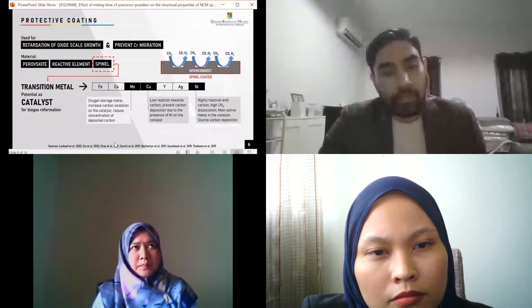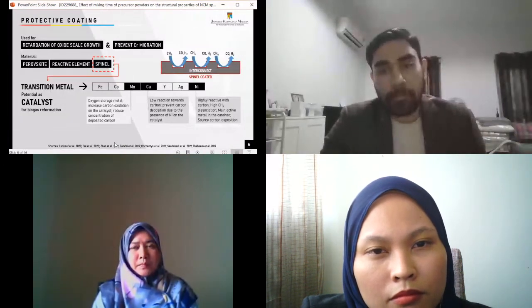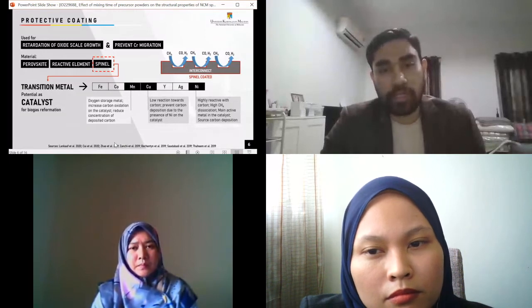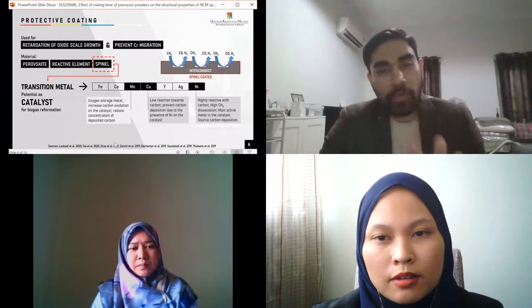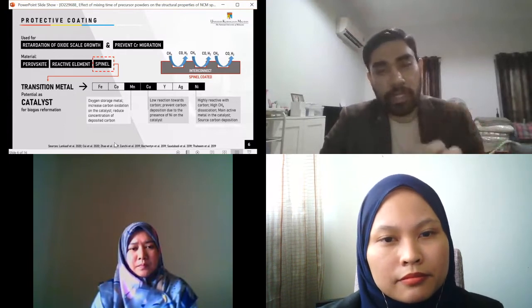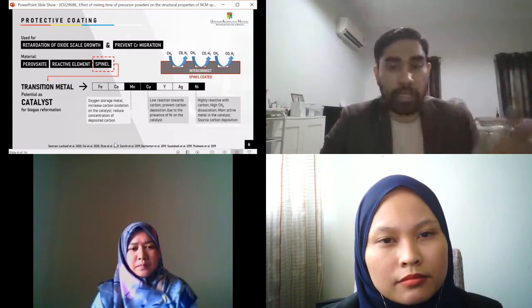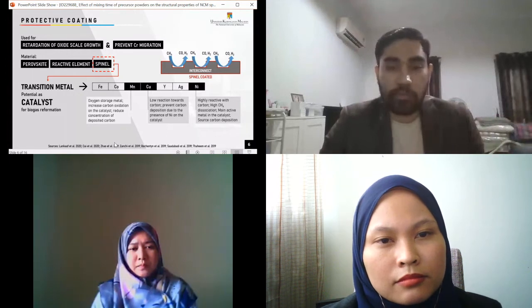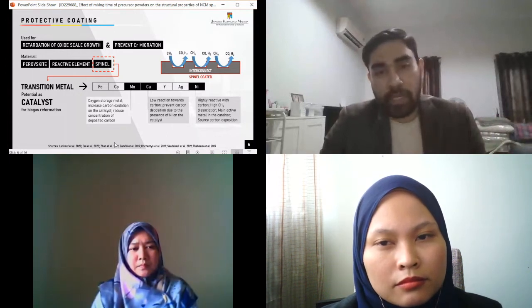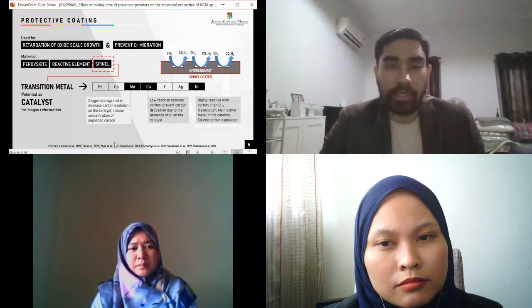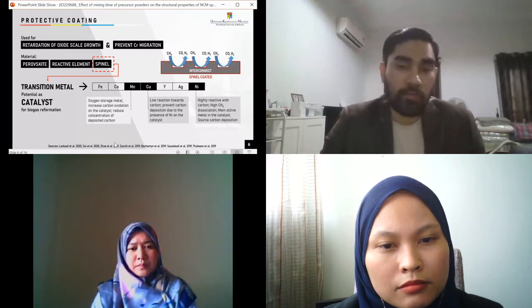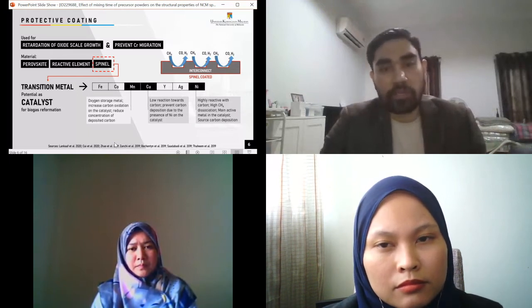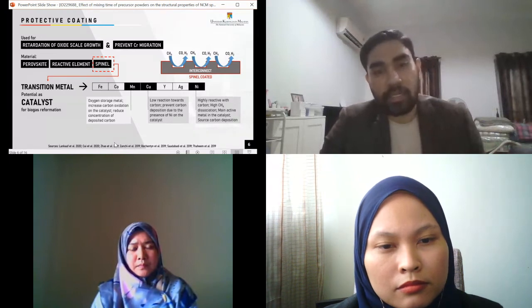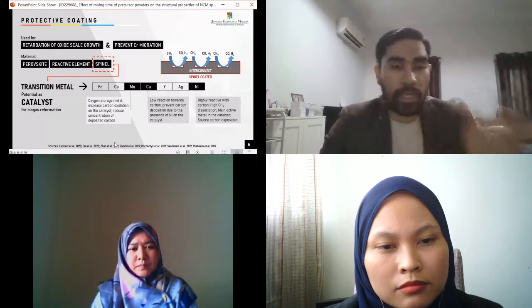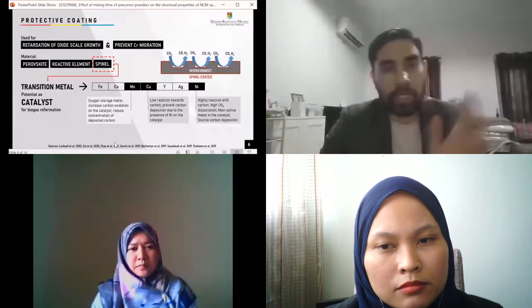In recent reports, there are findings showing that oxide scale growth can also occur at the anode side. Even though the growth is not as rapid as on the cathode side, it can still contribute to the poisoning of the anode, which can degrade the cell and also lower the performance of the solid oxide fuel cells. So in our project, we suggest the coating not only at the cathode side, but also at the anode side.